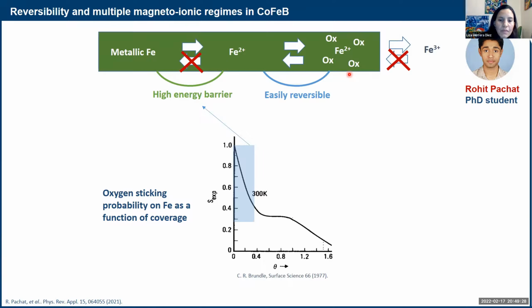Here we see that there is a part where this oxygen sticking probability doesn't change a lot. We tend to attribute this maybe to a phase which just adds more oxygen. The iron is still iron 2+, but it's just accumulating oxygen around it. And then in the end, it would go to iron 3+. This is actually what they say in this study, that at the very end, they get iron 3+. And what I showed you up to now, the regime 2, is probably between these two. Here you don't really have a change in the oxidation number. It's just iron with a chemical environment with less or more oxygen.